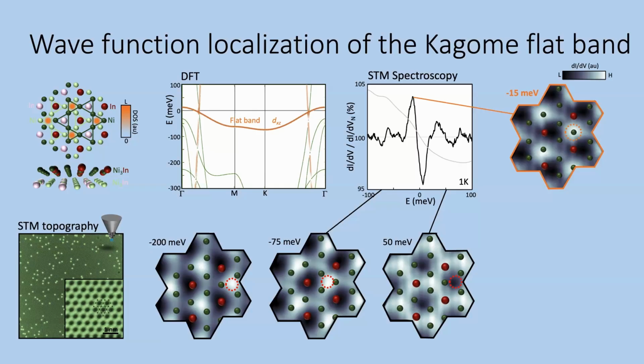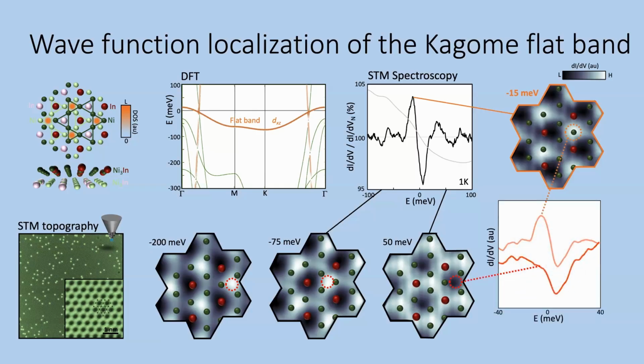And now, after we have this high resolution of every pixel within this unit cell, we can go to specific points within this super resolved unit cell and plot the full spectrum at this exact point. And this is what I show on the bottom right. So on the nickel sites, the orange curve, we see very clearly the peak, the flat band localized.